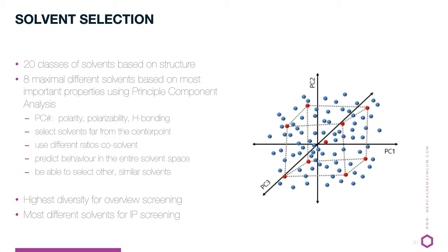In all steps, the solvent selection is key. A limited diversity will only show a small selection of the possible forms that can grow. For your selection that is based on a solvent structure or the active group of the solvents, that results in about 20 different classes. The identification of the solvents based on principal component approach gave three most important properties: polarity, ability to get polarized, and the hydrogen bonding. Combination of these three properties gives you 8 different solvents at corner points and optionally one center point, as indicated in the figure to the right.